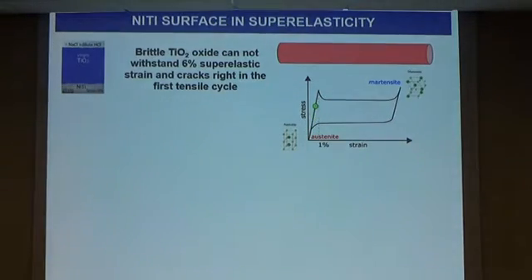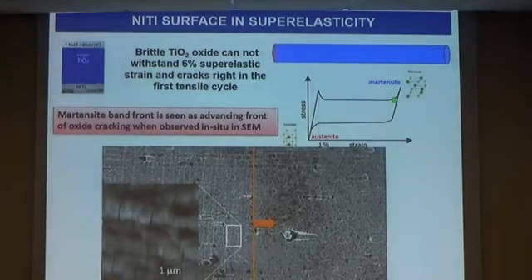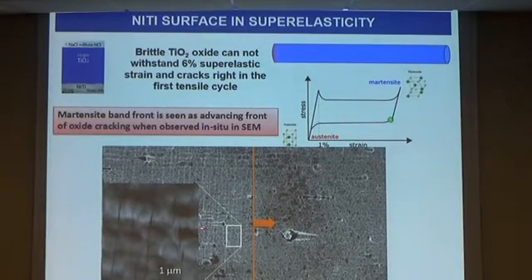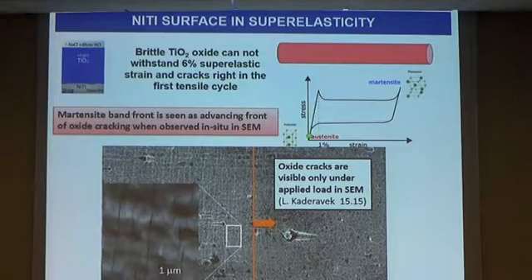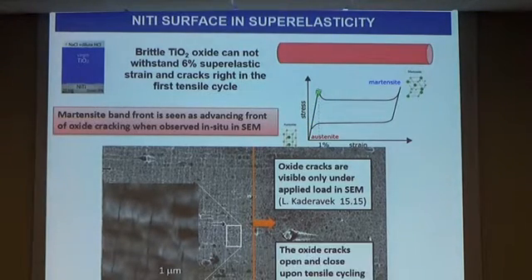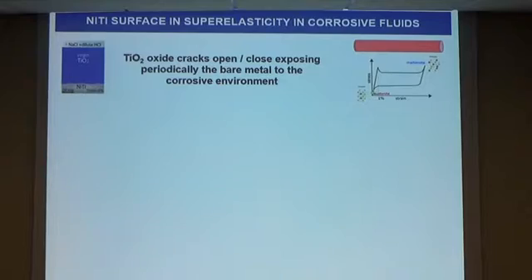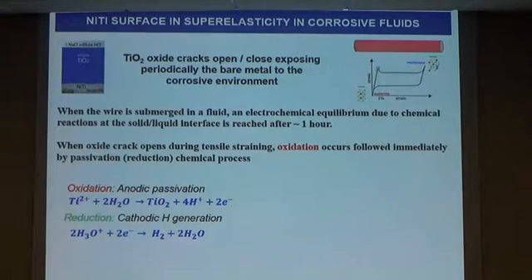The problem starts when it's dynamic. When you submerge the wire into the fluid and start to cycle it, immediately, not only will the oxide crack, but it will crack in millions of such tiny nanometer size cracks, which upon cyclic loading then periodically open and close, and you are like in a house where you want to be protected against the cold, but the doors are open and close every 10 seconds, which is not probably so easy.